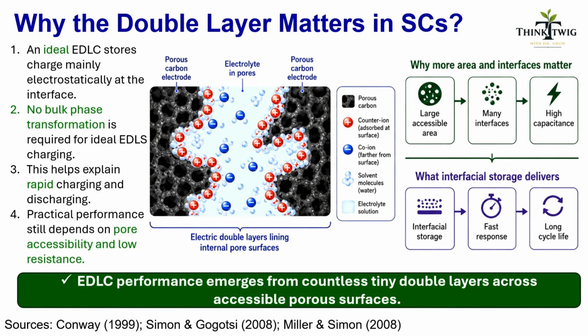Now we can connect this entire discussion with the working of an electric double layer capacitor. A porous carbon electrode contains a very large number of internal surfaces. Whenever the electrolyte reaches these surfaces, a double layer can form, and each small interface behaves like a tiny charge storage region. One such interface stores only a very small amount of charge. But a porous electrode contains countless interfaces. Together, they produce the measurable capacitance of the device. In an ideal EDLC, charge is stored mainly through electrostatic separation. There is no required bulk phase transformation during ideal double layer charging. This helps explain why an EDLC can charge and discharge rapidly.